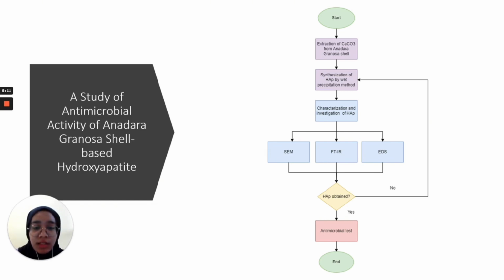And then the solution is left to age at room temperature for 24 hours before we centrifuge and wash the solution to obtain HAP gel. The gel is then put into the oven to get HAP powder before it undergoes the calcination process for 6 hours. And then the HAP powder is characterized by SEM, FTIR, and EDS. SEM is used to study the morphology of the HAP particles. FTIR analysis is performed to identify the functional groups of the HAP powder. Meanwhile, EDS spectra is used for the elemental analysis of the HAP powder. After the characterization, we can conclude if we have obtained the HAP powder or not.